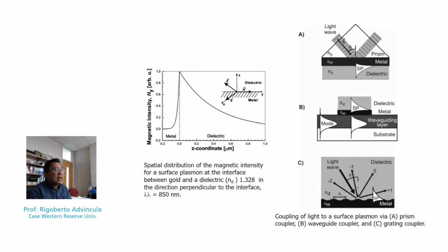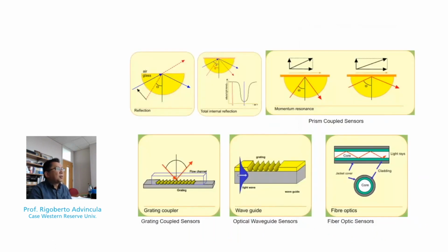And then finally, light can be excited using a grating. This is a substitution for a prism, where again, depending on the impinging light or the angle, one can excite the surface plasmon. Essentially, the waveguiding and the surface plasmon are related to attenuated total reflection in many optical experiments. So again, here you can see some of the interpretations of an SPR ATR experiment.